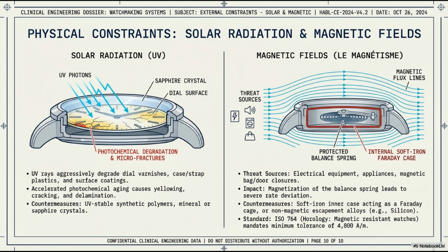On the right, magnetic fields, or magnetism. This is arguably the most common modern threat. Our homes are filled with electrical equipment, speakers, and magnetic bag closures. What is the impact? If the microscopic steel balance spring inside the movement becomes magnetized, its coils will attract each other. The watch will run violently fast, gaining minutes or hours a day. Our countermeasures? We either encase the movement in a soft iron inner shell acting as a Faraday cage to route magnetic flux lines around the caliber, or we utilize entirely non-magnetic escapement alloys, like silicon. ISO 764 mandates a minimum survival tolerance of 4,800 amperes per meter.